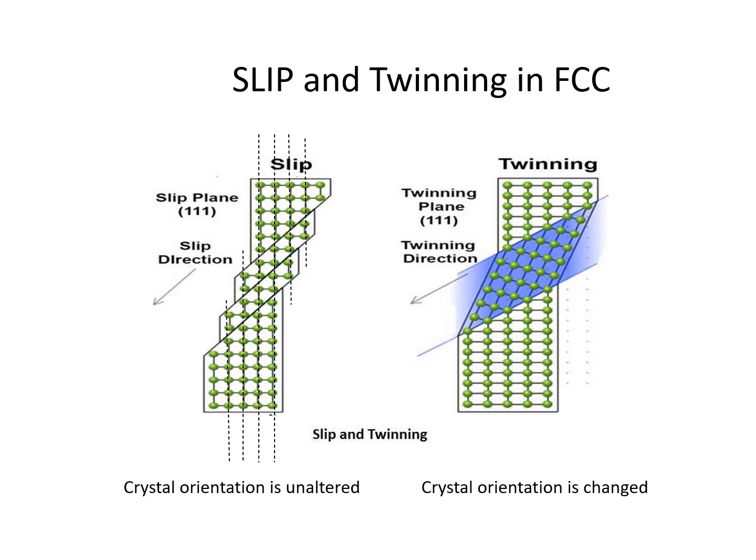Twinning, on the other hand, if you do a similar kind of shear operation, as you would by having multiple shears of perfect dislocations along a given slip plane, in twinning you do change the orientation of the crystal, as illustrated here. And we'll talk more about that, and I'll illustrate that in the videos.